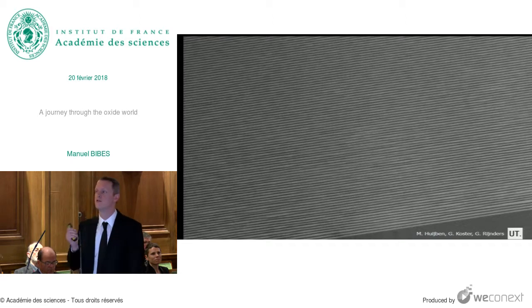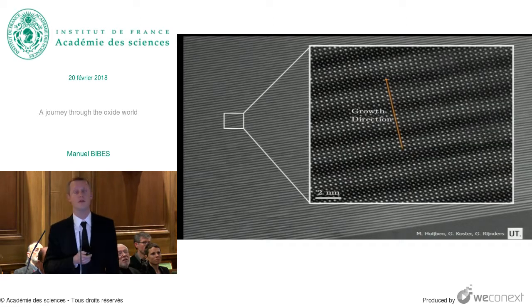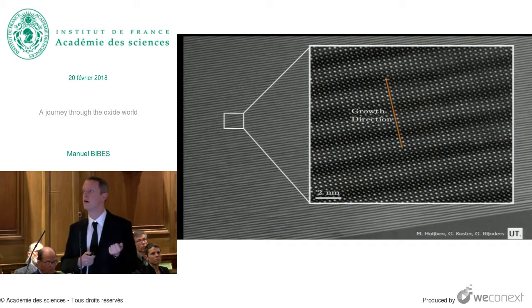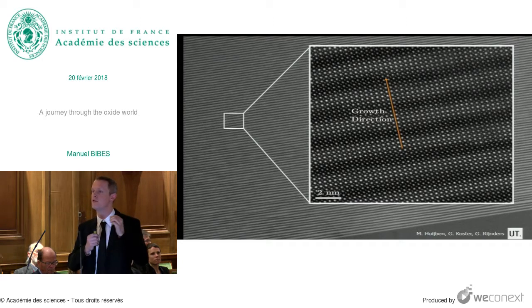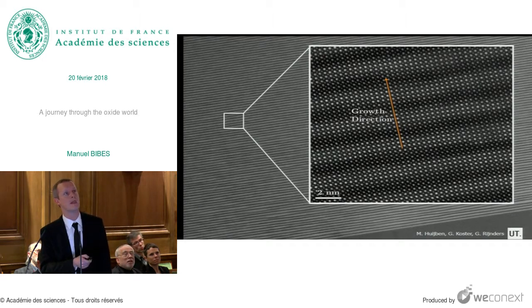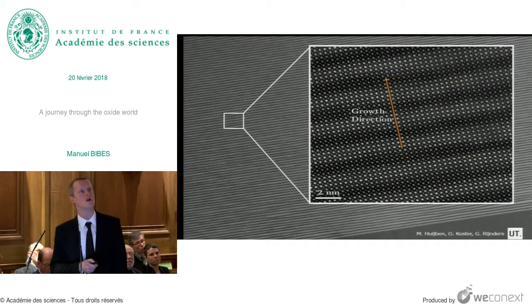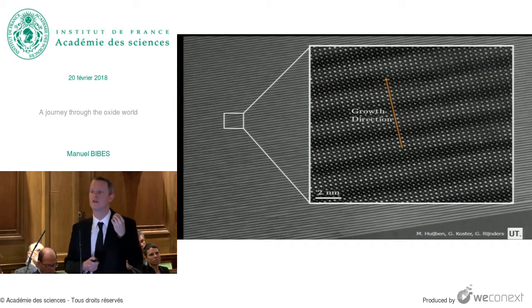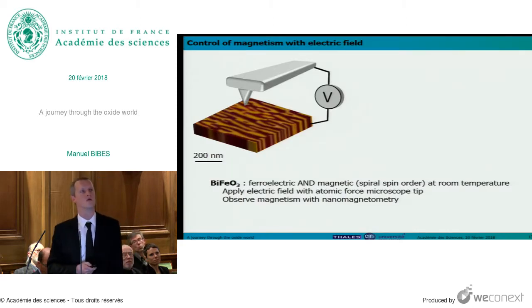This is actually a transmission electron microscopy image of one of these multilayers. If you zoom in, you see that the white regions correspond to one material, for instance the blue material before, and the dark regions correspond to the pink material. They show with brighter or darker contrast because they are different elements that respond differently to the microscope. And each of these small dots is actually a column of single atoms, for instance a lanthanum atom, a titanium atom. So it gives you a flavor of the control that can be achieved to grow these quantum materials.